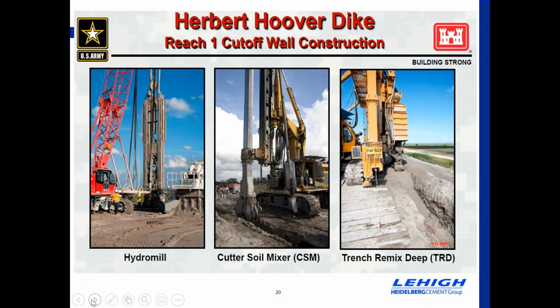So all variations on a theme. What we're looking at is, most of you have seen hydromills, cutter soil mixers, or TRD machines. Ultimately, what we're doing is mixing a cement slag slurry with the existing ground conditions, allowing that to solidify, looking for relatively low strength, 500 to 800 psi, but looking for very low permeability. And that's the reason why that mix has gone to such a high proportion of slag cement.